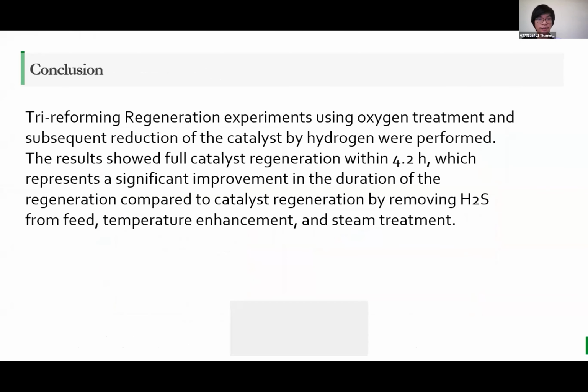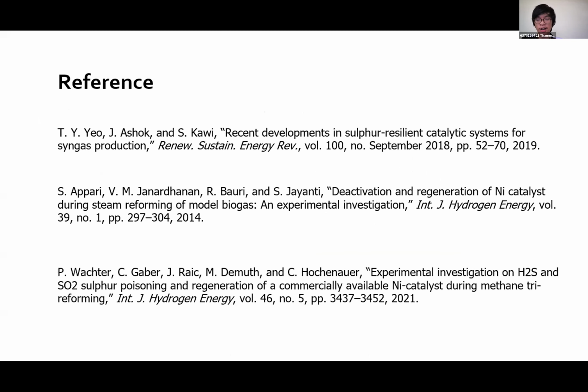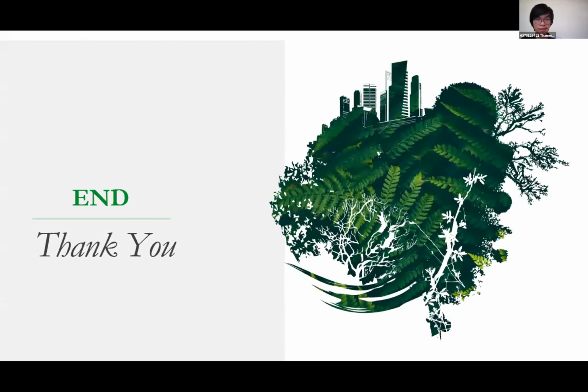Conclusion: the tri-reforming regeneration experiment used oxygen treatment and reduction of the catalyst by hydrogen. The results show full catalyst regeneration within 4.2 hours, which represents a significant improvement in the duration of regeneration compared to catalyst regeneration by removing hydrogen sulfide from the feed, temperature enhancement, and steam treatment. All of the content can be found in the reference research paper. Thank you for your attention.